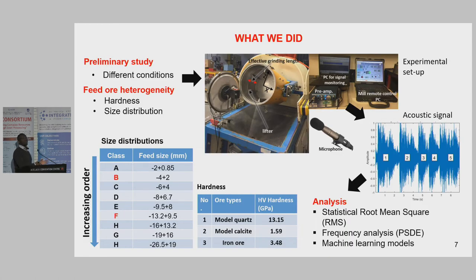What we actually did to come out with our findings: we tested different mill operating conditions and analyzed their acoustic intensities or characteristics as a preliminary stage study. Then we moved a step further to investigate feed ore heterogeneity in terms of hardness, where we considered three ore hardnesses: model quartz as the hard mineral, model calcite as the soft mineral, and iron ore as the intermediate hard mineral. Then we also tested the size distribution to see its impact on the acoustic response during grinding. We also looked at their blend ratios, the size distribution, their blend ratios and acoustic responses.